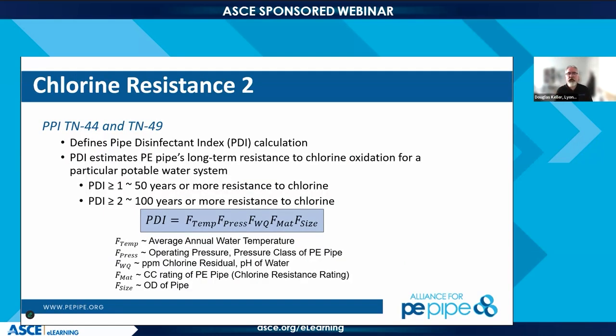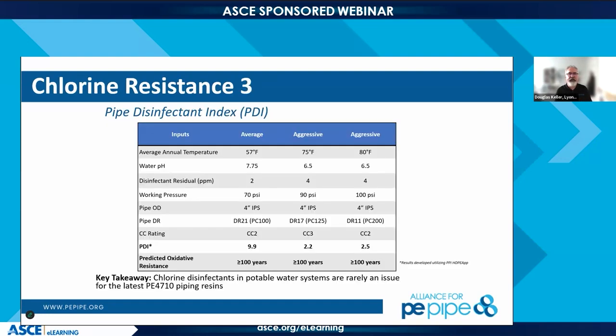We have done a lot of work on chlorine. The earlier generation materials that had 1 hour, 3 hour, 10 hours of PENT were more susceptible to chlorine resistance failures. We did a lot of work as the Plastics Pipe Institute looking at small diameter and large diameter pipe in order to design and understand what happens with chlorine. So in most cases, and we'll see this on the next slide, chlorine is not going to be an issue in the distribution system.